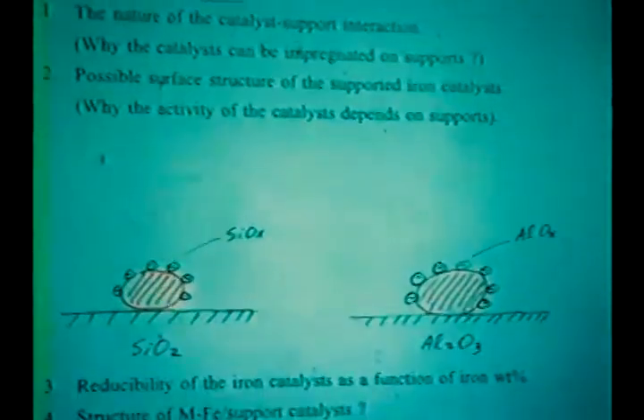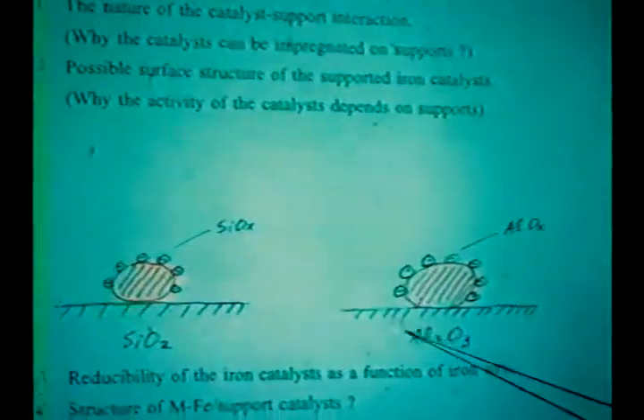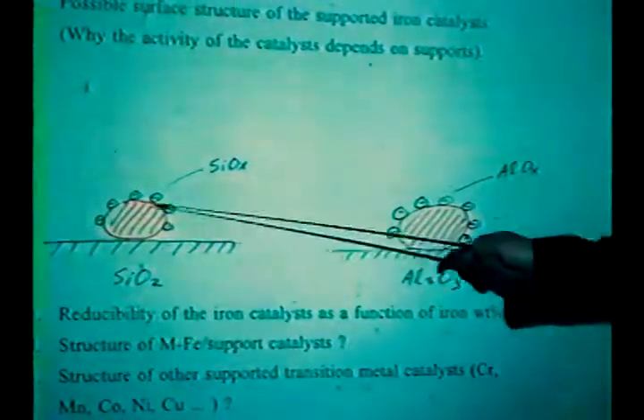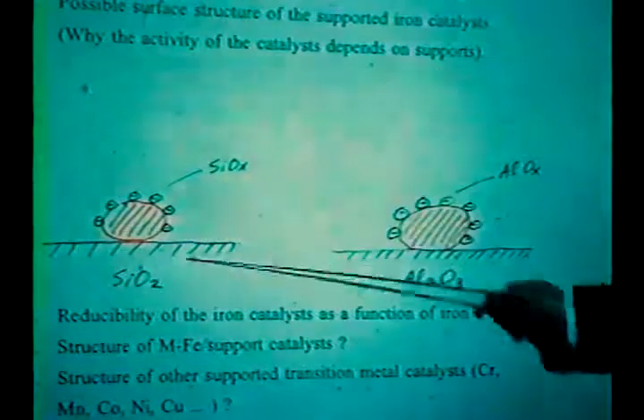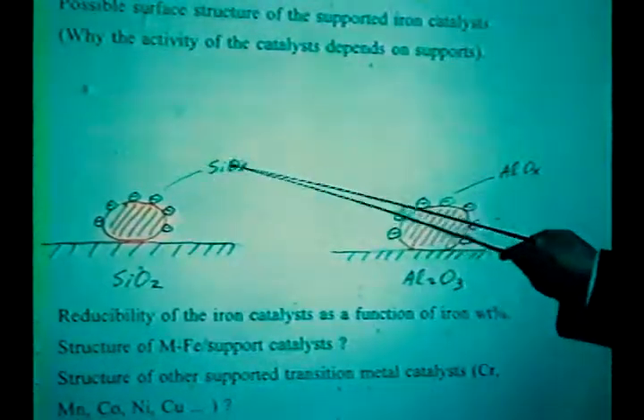Another question is why the activity of a catalyst depends on support. I think Professor Carmen Bettmuller raised this question. He said, why do you have iron catalysts on silica and aluminum, but the activity is different? Now, using the impregnation method, the incipient wetness impregnation method, inevitably some silica ions will be dissolved in the solution, and these silica ions can be deposited at the surface of the iron oxide. If you look at the surface for the aluminum oxide iron catalyst, this is the iron oxide particle, and it is covered by aluminum. So of course these two are different.